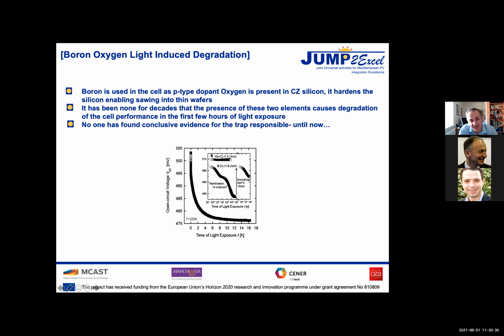The other interesting thing here is that they did a comparison with gallium. Gallium does not degrade, or maybe it does. So this is something else we're looking at, and manufacturers are going over to gallium because it gets around this problem. But gallium has its own problems. Gallium does not diffuse well in silicon, so it's more difficult to get uniformity of doping, and those problems are being looked at and they're being overcome. But it's not simply a case of replacing boron with gallium. The other prospective dopant is indium, but indium also has its own problems. Indium's quite interesting because it's controversial whether it degrades or not. We don't think it does, and some people do think it does. That's a different story. But indium's also a very scarce element, as we mentioned, so we best avoid it.